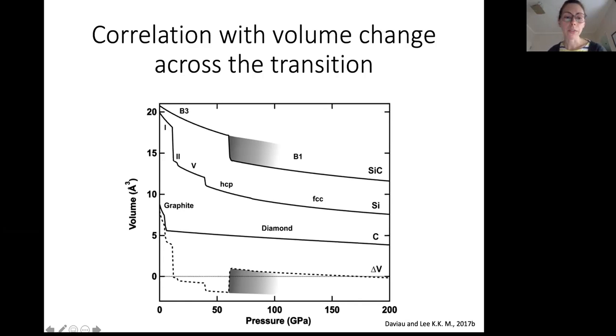Right, so silicon carbide at the top, as we showed before, goes through that jump in density, or drop in volume, from the B3 to B1 transition. Silicon goes through many different phase transitions at lower pressures, each with a density increase. And then carbon, of course, goes through the famous transition to diamond, again with a big density increase. And so if you combine all of these phases and consider the change in volume for silicon carbide to go to silicon plus carbon, what we get is in this dotted line here.